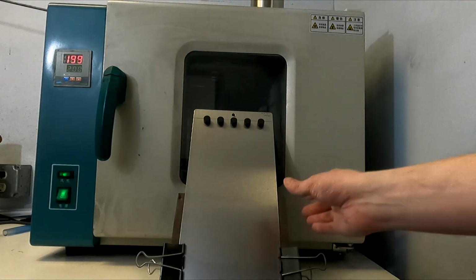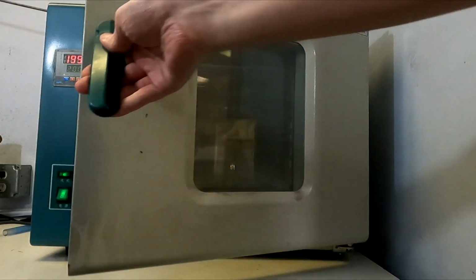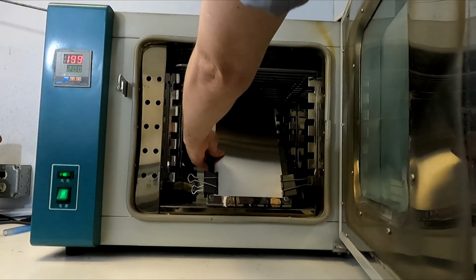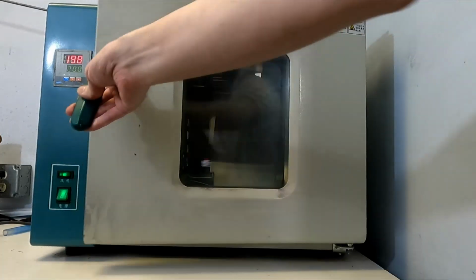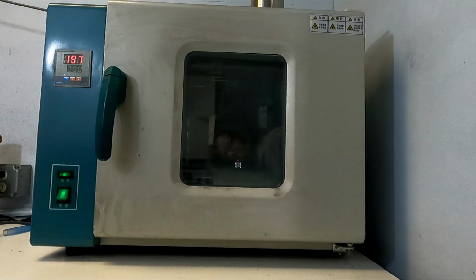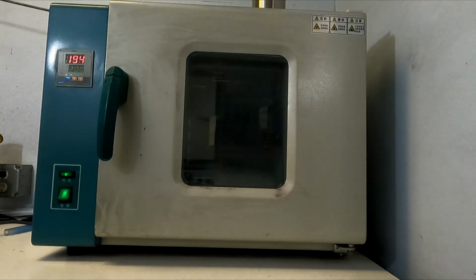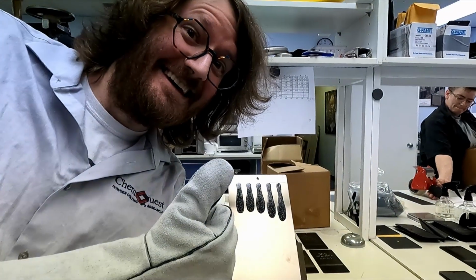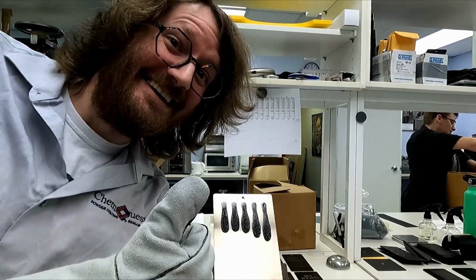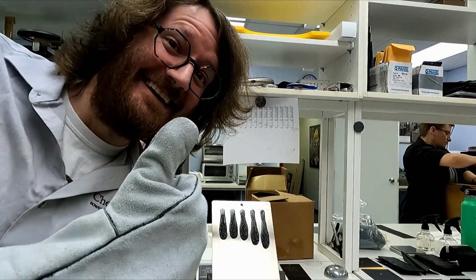Generally speaking, although for various reasons these aren't hard and fast rules, for powders with the same rate of cure, a longer pellet flow indicates lower melt viscosity, which could result in the coating being more smooth, having less texture, and potentially a higher gloss. A shorter pellet flow is indicative of higher melt viscosity that may have more texture or result in increased coverage over sharp edges. For these reasons, an inclined plate flow test is a great way to confirm consistency between batches of the same coating, as well as to infer performance differences between a series of coatings that have a variable.